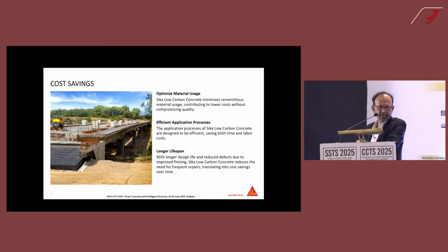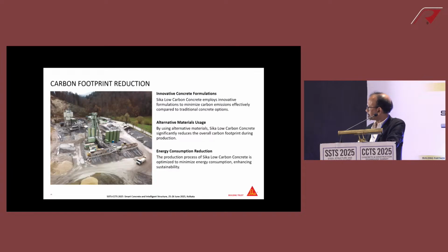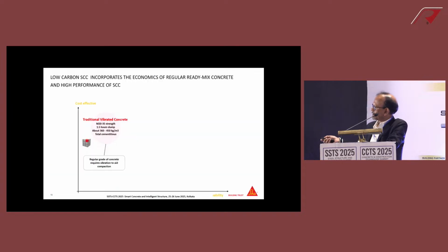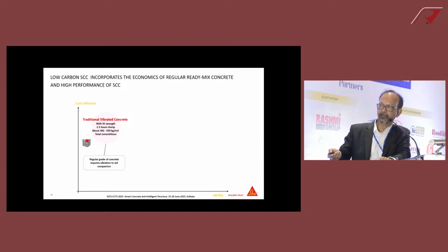Before, if I had to design 30 MPa concrete, I used to have 600 kg per cubic meter of fines, which is less than 150 micron. Today, I can do it with 450. Huge cost saving, because bulk of it is supplementary materials and cement. And this will actually lead to longer lifespan. So this is just to give you an idea about the cost effectiveness versus the flowability.